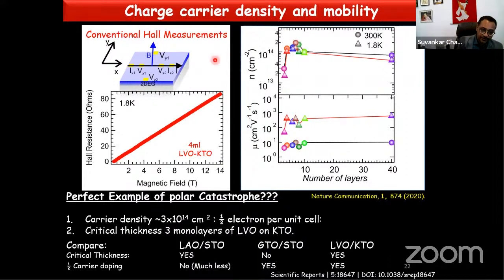doped per unit cell. So let me give you a comparison with known systems, and you can realize that this is a really perfect example of polar catastrophe. If you think about the lanthanum aluminate and strontium titanate system, it has a critical thickness, but it has a charge carrier density less than half an electron doping. If you think of the gadolinium titanate strontium titanate interface, it doesn't need any critical thickness, but it has half an electron doping. But in our case, lanthanum vanadate and potassium tantalate, both criteria have been satisfied: it needs a critical thickness and it has a half electron doped system.